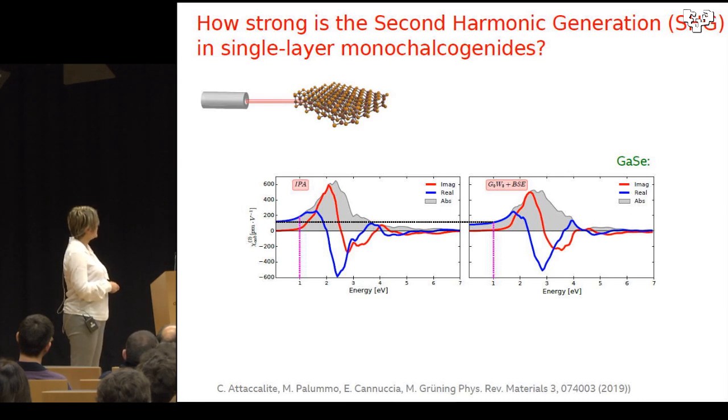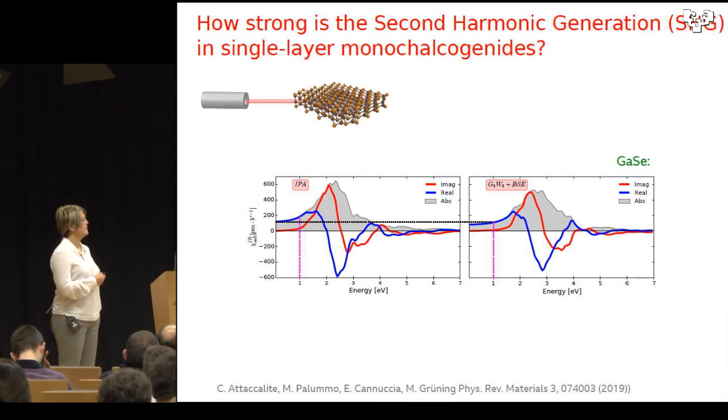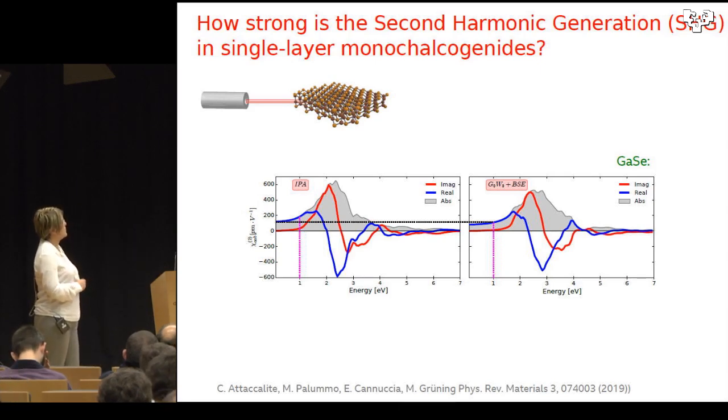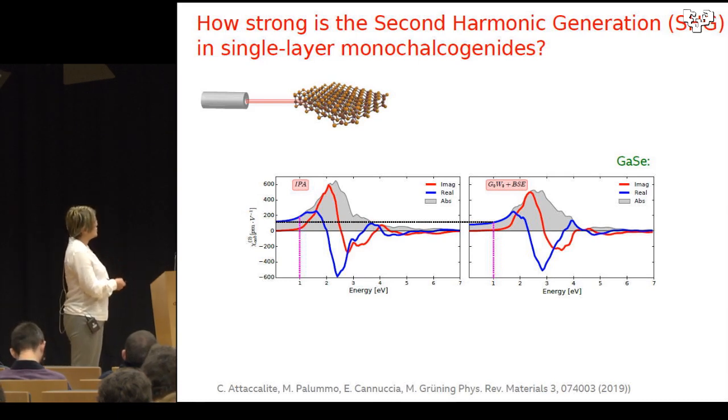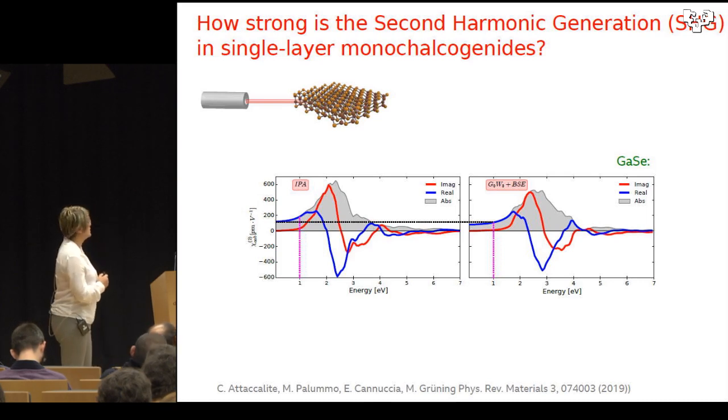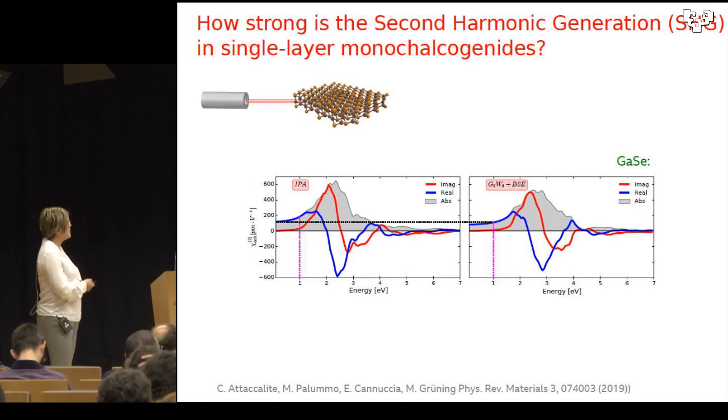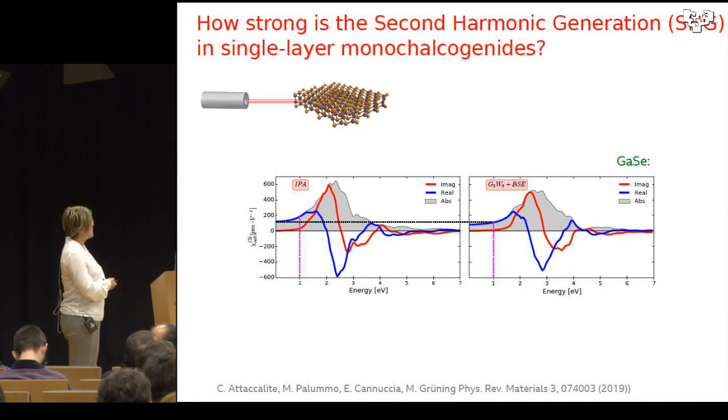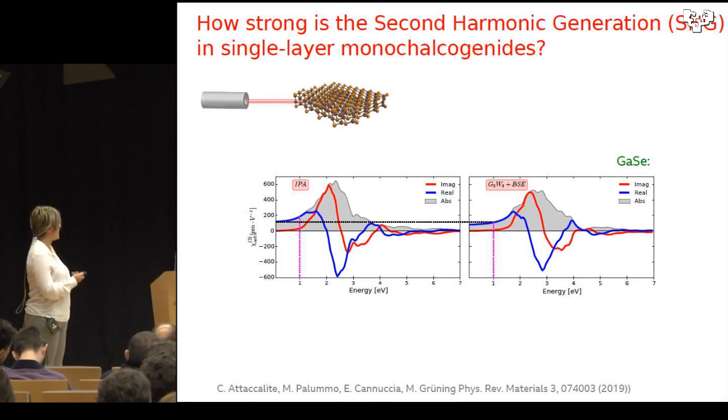And again, here I show where the measurement was taken, and you actually see that in independent particle we would get a larger value than what we would get with G0W0 plus the Bethe-Salpeter, just for this effect of adding the G0W0 that diminished the coefficient, and then the Bethe-Salpeter just gets a bit more at excitonic resonance. For example, here it's larger, but still everything is at the same order of magnitude.